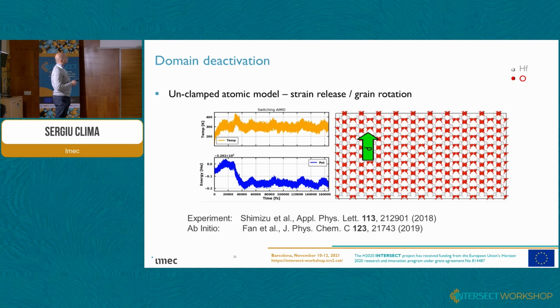Afterwards, it actually transforms into a monoclinic dual grain model. I was quite intrigued by this simulation, but then we found that there is some experimental evidence for this polarization rotation of 90 degrees, and also an ab initio work where they witnessed exactly this type of 90 degree rotation for the ferroelectric domain.